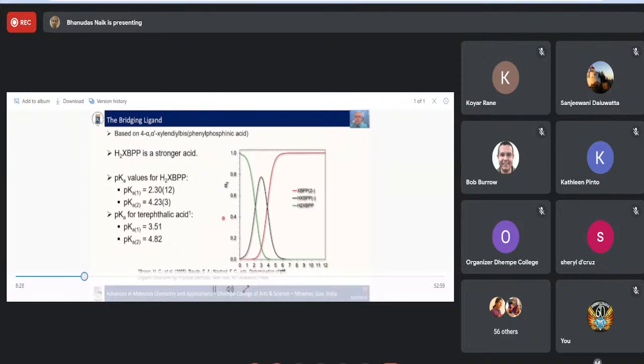The distribution of each component can be calculated based on the pKa's, and you can see that if you have a very low pH, a very acidic solution, less than pH of 1, you basically have the acid in solution, and it's actually not really soluble. It's very difficult to dissolve in a very acidic solution. But as you increase the pH slightly, you begin to form the monoanion, a monoprotonated anion, which only exists between basically pH 2 and pH 4. As you increase the pH above 3, you begin forming the dianion, and the protonated acid goes down to 0 above pH 4.